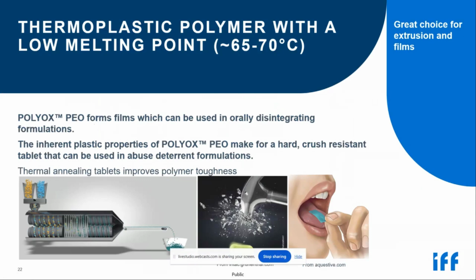Pairing that hard to crush and hard to grind with the fact that a high molecular weight PEO swells significantly makes it advantageous in abuse deterrence, in deterring both crushing into a powder for sniffing up the nose, or crushing to a powder, putting into water to hydrate, and then extracting the active using a syringe and trying to inject it. It becomes really thick and viscous, and it's very difficult to take up with a syringe and to then inject into the body. So those two properties are why it has been historically used in abuse deterrence.